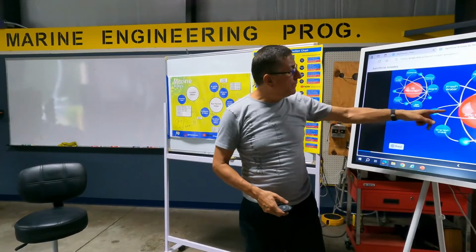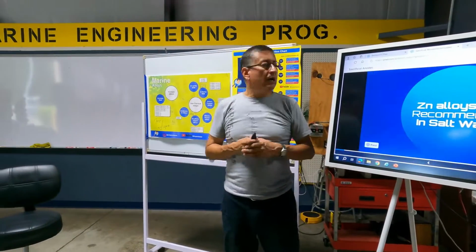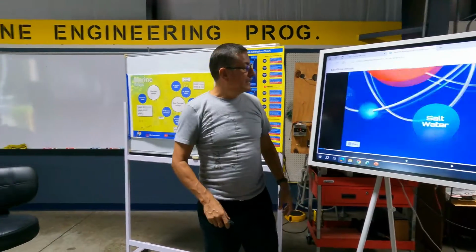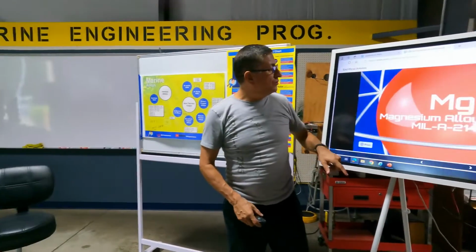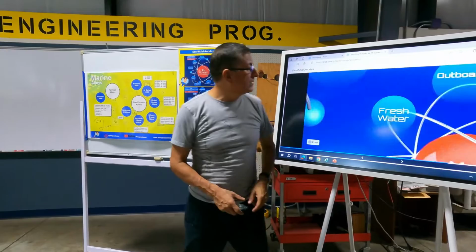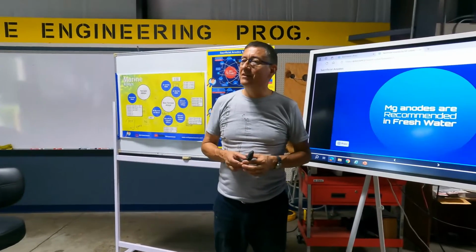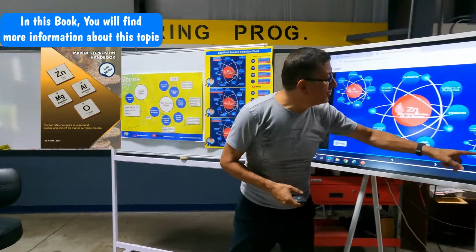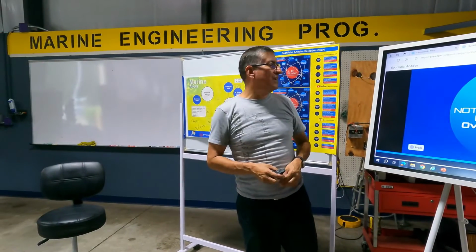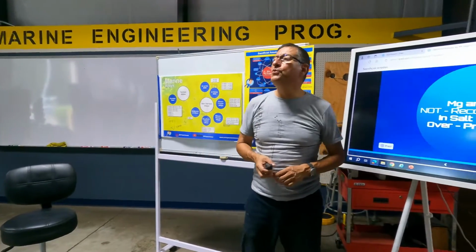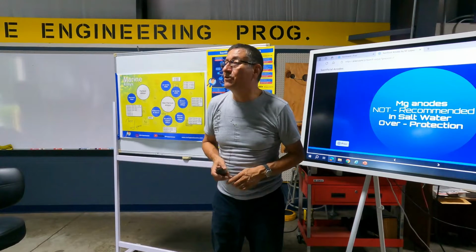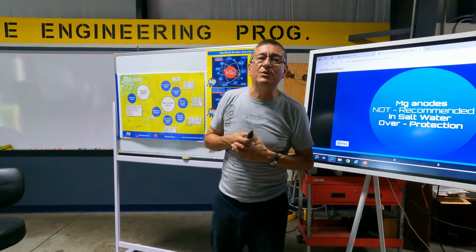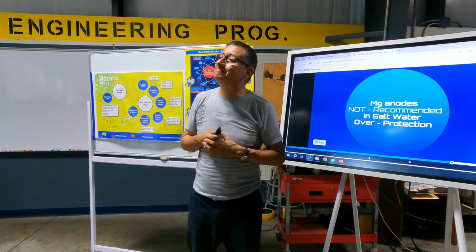Okay, nice. Let me check what happened with zinc in salt water. Zinc in salt water is fully recommended. Nice. Okay, let me check magnesium. Magnesium in fresh water. Recommended. Magnesium alloys in fresh water, fully recommended. What about magnesium in salt water? Not recommended in salt water because it produces overprotection, because it's highly anodic, and salt water is an excellent conductor of electricity.